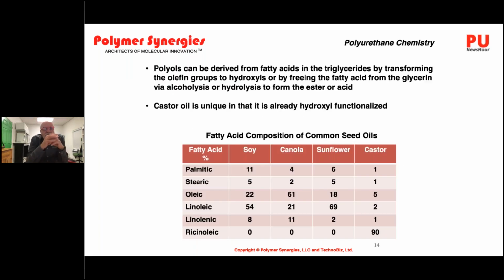When we talk about polyols that are derived from these fatty acids and triglycerides from different oils, they will vary in the fatty acid composition. For example, if we look at soy, this is the composition of the fatty acids, where it's very high in linoleic and oleic composition. If we compare that to another oil, we see that oleic is higher than the linoleic, but it's got a similar structure. And then we look at sunflower, it also has high linoleic and oleic. So it's these double bonds that are functionalized that allow us to make our polyols from these fatty acids. Castor is very unique in that it is primarily ricinoleic acid, which is already a functionalized polyol.